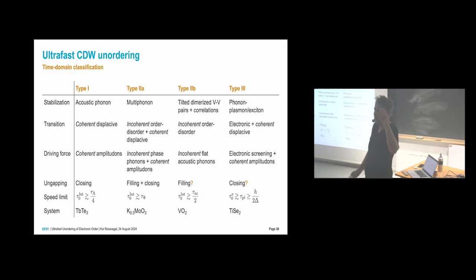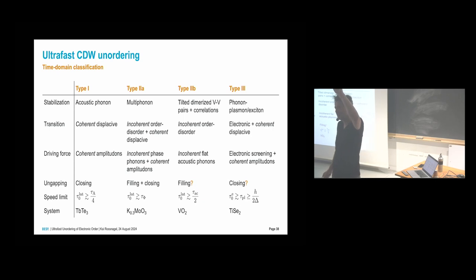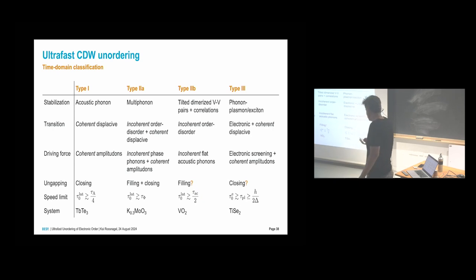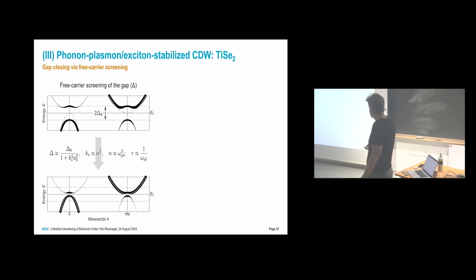Yes, but in these materials, they are more metallic than titanium diselenide. And there, the plasma frequencies are on a much higher energy scale, let's say 1 electron volt or more. And then your excitation doesn't change that so much. Here in titanium diselenide, in the excitonic insulator business,